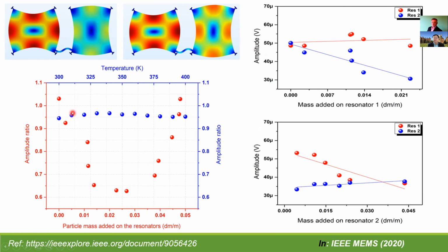So if we look at this graph, when particles were deposited on the first resonator, the amplitude ratio varied, which shows the amplitude ratio output metric is sensitive to the mass deposited on the first resonator. Similarly, when mass was deposited on the second resonator, the amplitude ratio varied again. It also proves that the amplitude ratio shift output metric is sensitive to the mass deposited on the second resonator.